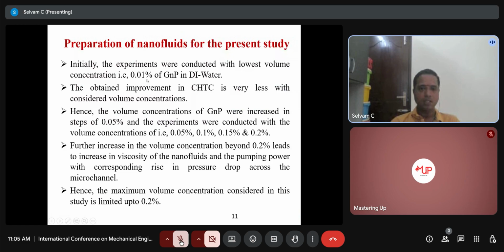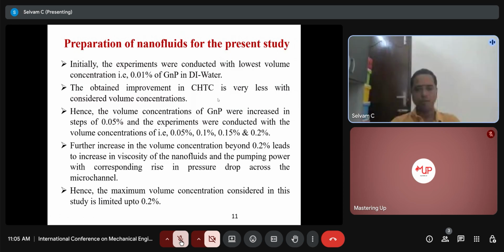And we have conducted the experiment and we have found that the improvement in convective heat transfer coefficient is very less. So after that, we have fixed the volume concentration with steps of 0.05%. From 0.05 to 0.2 with steps of 0.05 we have varied, and these concentrations have been fixed. Beyond 0.2 the pressure drop will increase, and because of the pressure drop, pumping power will be increased. So as per the literature also we have restricted up to that point.